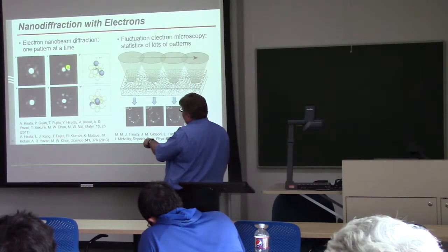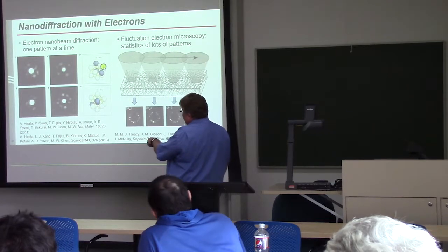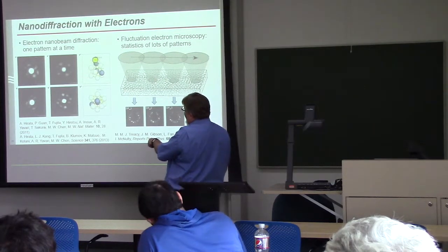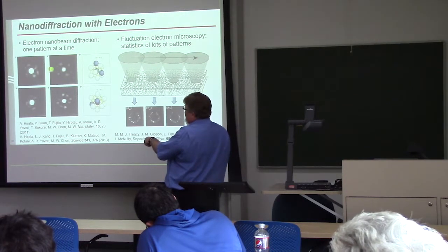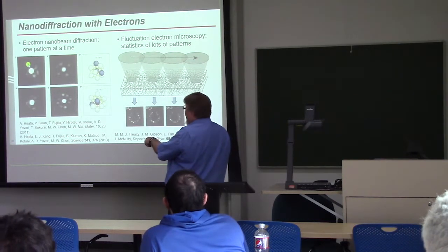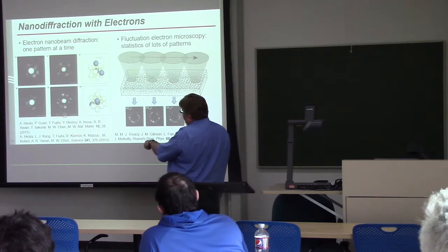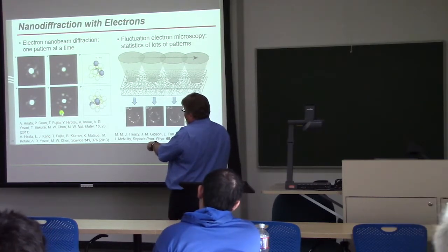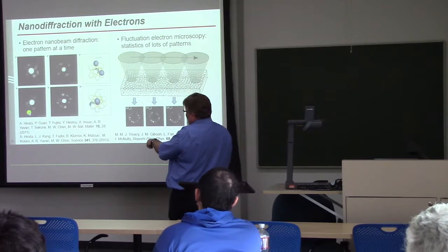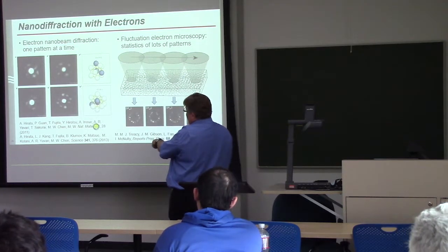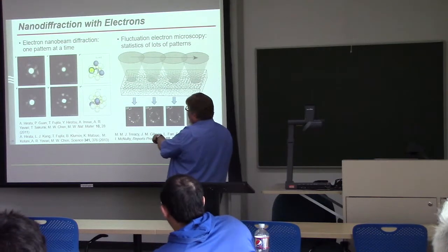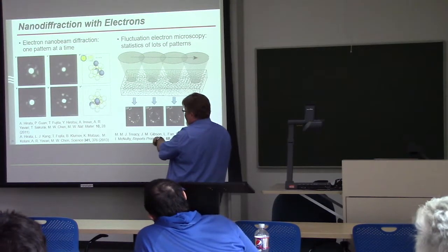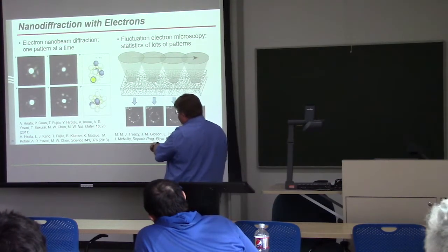And on the right-hand side are simulated diffraction patterns from the clusters shown on the far right in a particular orientation selected to match the experiments. So what this allows the experimenters to do is to say, we have uncovered evidence that these clusters exist somewhere in our glass by this kind of matching process, one-to-one.